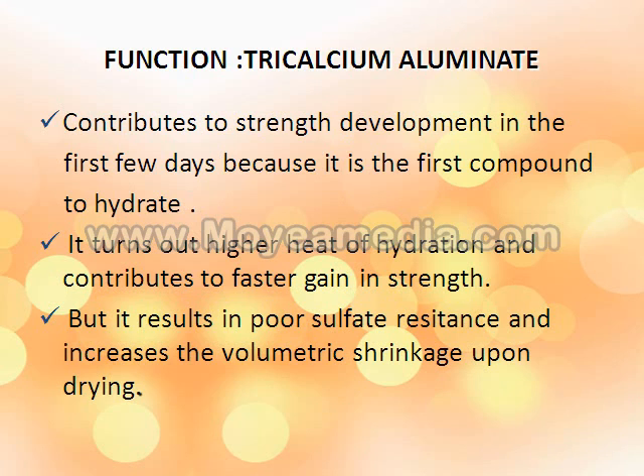Functions of tricalcium aluminate. It contributes to strength development in the first few days because it is the first compound to hydrate. It turns out higher heat of hydration and contributes to faster gain in strength, but it results in poor sulfate resistance and increases the volumetric shrinkage upon drying.